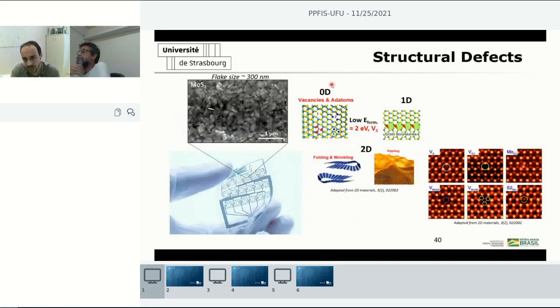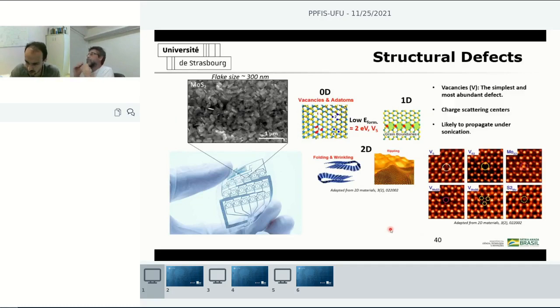But this kind of material can also present structural defects, and the types of defects one can have are 0D defects, which are vacancies, and these vacancies form at very low energies, around 2 electron volts, for example, for sulfur vacancies in molybdenum disulfide. You can also have linear defects, and also what the literature calls 2D defects, when you have folding of the flakes or rippling. Here is an illustration of the types of vacancies one can have, like single sulfur vacancies, double sulfur vacancies, molybdenum vacancies, and so on and so forth.